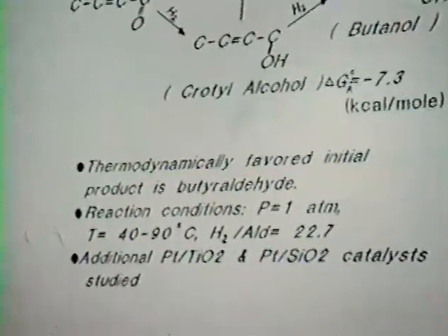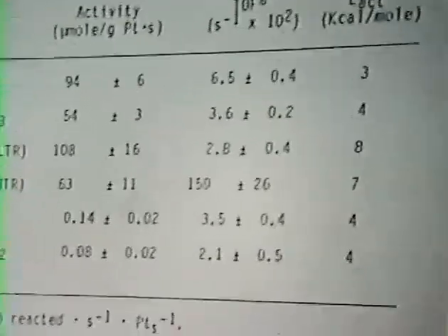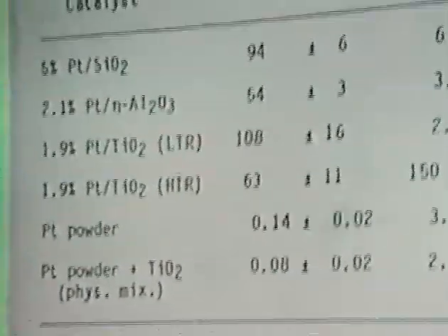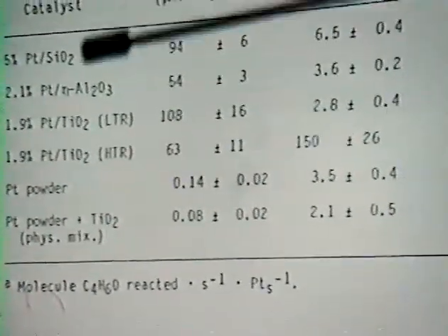I might also mention here that with regard to our results, and as indicated by the thermodynamics, platinum catalysts are not the best catalysts for that reaction. The literature teaches very quickly that these catalysts are very good for the formation of butyraldehyde, and in essence, the platinum catalysts in the literature give you 100% selectivity to butyraldehyde. We observe the very same thing with our typical catalyst.